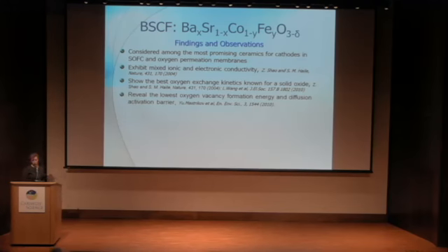For example, this whole series of BSCFs was considered among the most promising ceramics for cathodes in solid oxide fuel cells and oxygen permeation membranes, because it exhibits mixed ionic and electronic conductivity, which is good for these applications. It shows the best oxygen exchange kinetics known for any solid oxide. It reveals the lowest oxygen vacancy formation energy and a low activation diffusion barrier, which leads to very good properties for these applications. All these were good advantages, and that's why people were so enthusiastic about it.